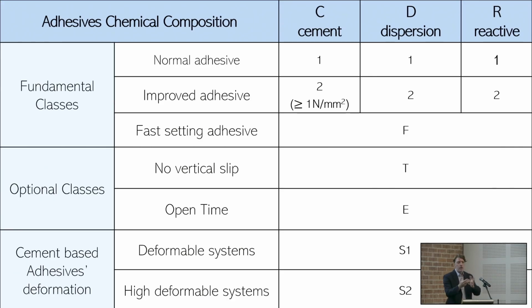Just a very common example. You have a stair made of metal. You want to cover it with whatever, marble, tiles, wood. Okay, you cannot use cement. You need to use the reactive. You have an elevator. Into the elevator, you have the basement made of metal. Sometimes it happens often. You can find, how do they fix the tile there? Not with cement, because cement is not fixing. So the reactive adhesive costs 3, 4, 5, 6 times more than cement, but can fix anything onto anything.